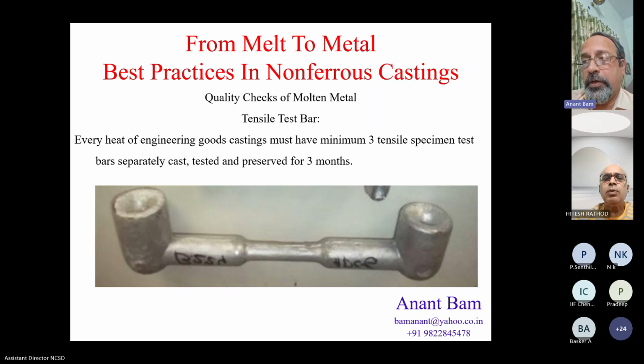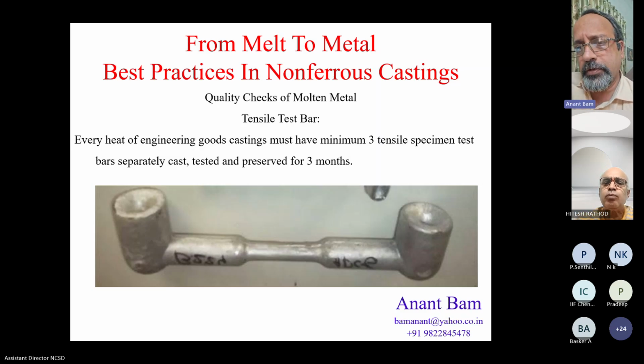It is a tensile specimen, a tensile test bar. For every heat of a critical casting or safety critical castings, or for any Government of India undertaking castings, let it be railway or any PSU casting, a minimum of 3 test bars per heat are recommended. This is a sample of a separately cast test bar. Sometimes you have to cast an integral test bar. Sometimes you have to take a test bar by cutting a casting, sacrificing that casting. It depends on the quality requirements of your buyer.